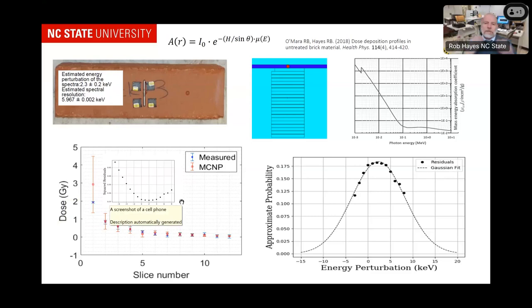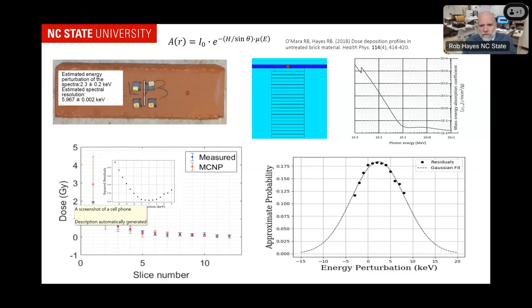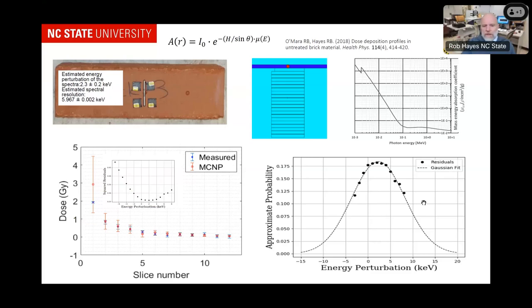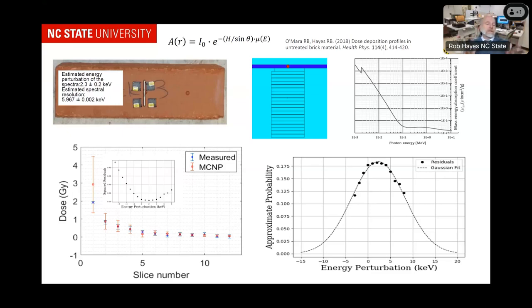If you assume that minimum is normal, inverting it would look like the top of a Gaussian. We fit those residuals to the top of a Gaussian to estimate the uncertainty. At the one standard deviation level — published in the paper — we empirically measured the mass energy absorption coefficient by that dose-depth profile and showed that at the one standard deviation level, the energy resolution was 10% for a brick. So we turned a brick into a gamma-ray spectrometer with 10% energy resolution capability for americium. This demonstrates what kind of ubiquitous gamma-ray spectrometry capability comes from retrospective dosimetry with ubiquitous materials.